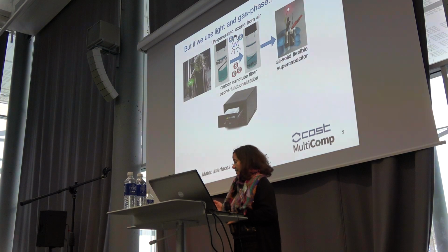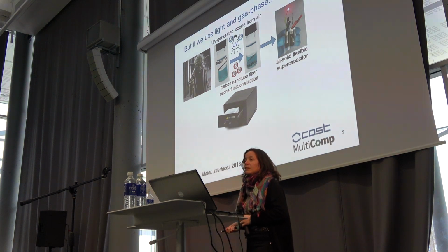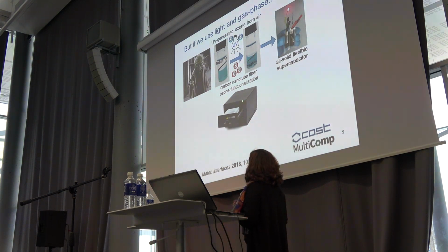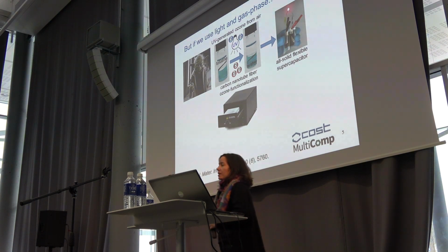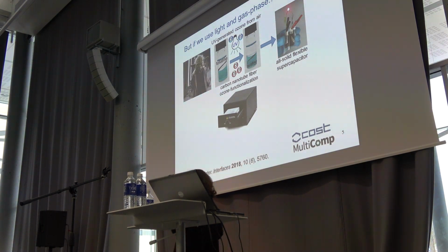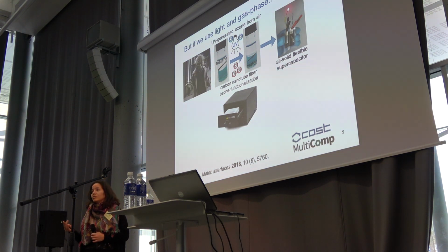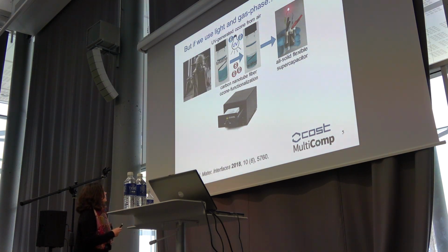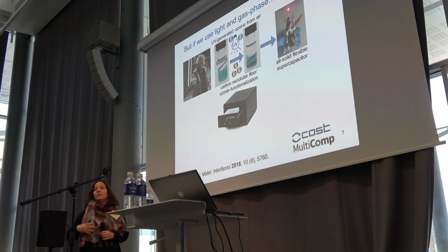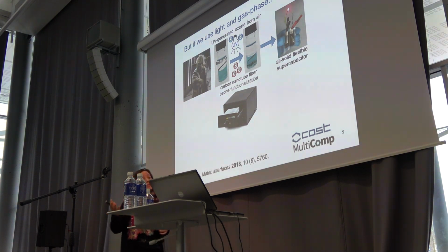So in this case, we used this very convenient and portable piece of equipment, which has simply a very powerful UV light inside with two different wavelengths, one at 185 nanometers and the other one at 254. What it does is that it produces ozone from oxygen that is contained in the air. You don't need any compressed gas cylinder or anything particularly fancy. And then you produce radicals from that, and of course the UV light gets absorbed by small molecules, or if your substrate has organic material, as was our case.